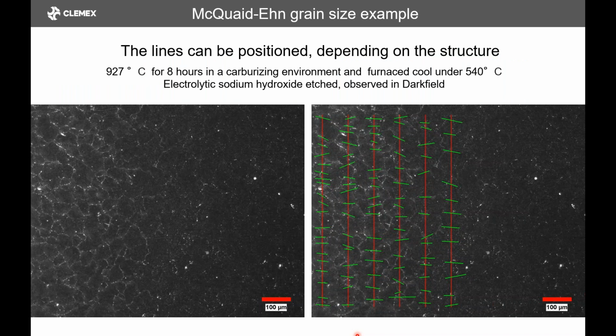Here's a different approach to line intercept. This sample was done with the McQuaid-Ehn method. Most of you are probably familiar with that: you heat up the steel at 927 degrees for 8 hours and put it into a carburizing environment so that the carbide will precipitate at the boundaries. In this case, it was electrolytically sodium hydroxide etched, and it's observed in dark field.